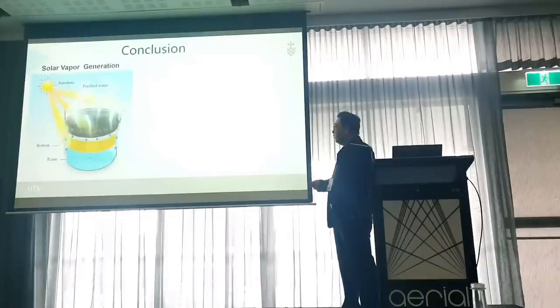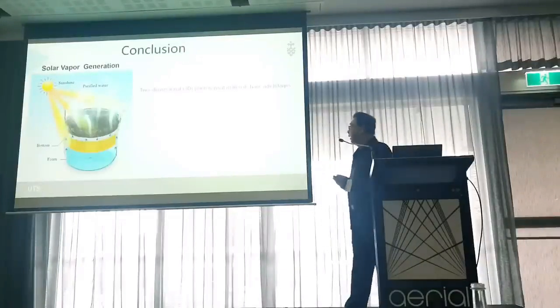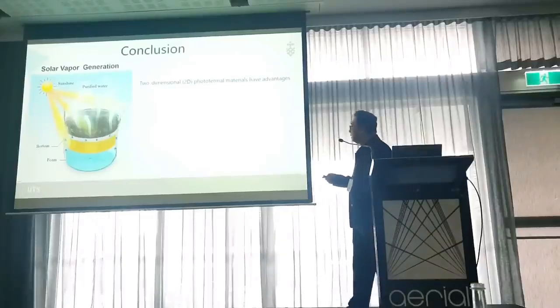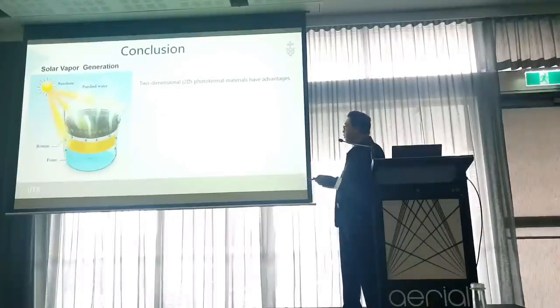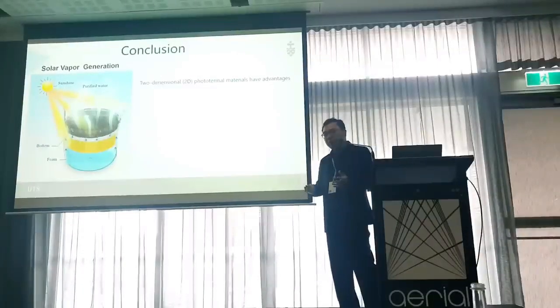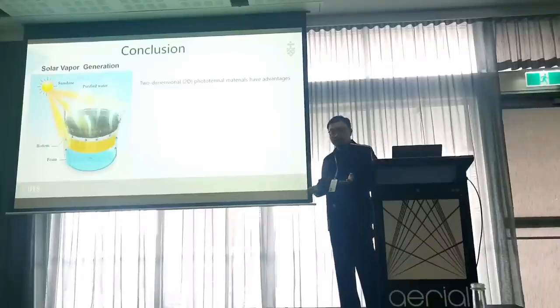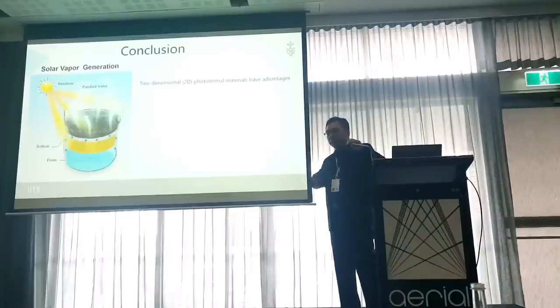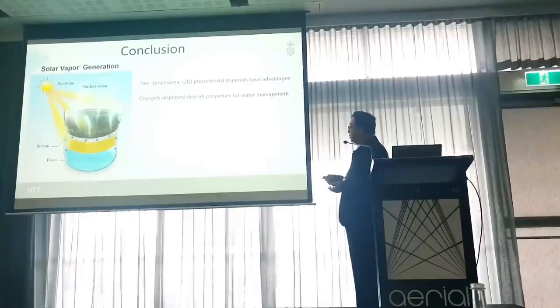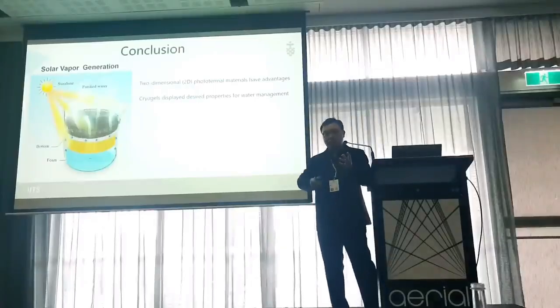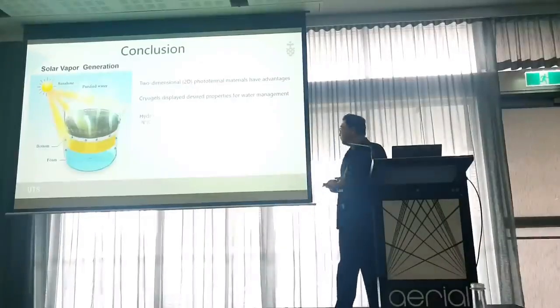So finally, to give a conclusion. Firstly, through our study, we found that 2D materials have a high aspect ratio, so they have some advantages compared to 1D and 3D photothermal materials, because we only need about 1/10 of the weight. And secondly, the cryogels also display the desired properties, like large pore size and interconnected pores.